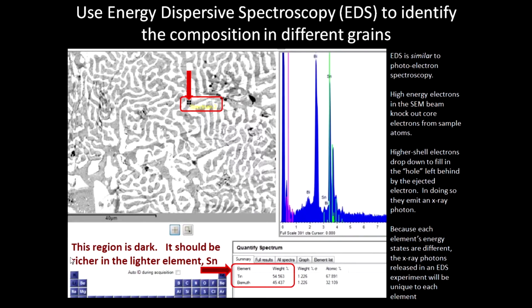And so down here at the bottom, it says the elemental composition. We've got the region is dark, and we predicted that that should be richer in the lighter element tin. And right over here on the right, it's a little bit blurry, but it says that this spot is about 54.6% by weight tin and 45.4% bismuth. And that does match our prediction, right? We said that dark areas should be rich in tin and have less bismuth. And that's what we see at this dark area.